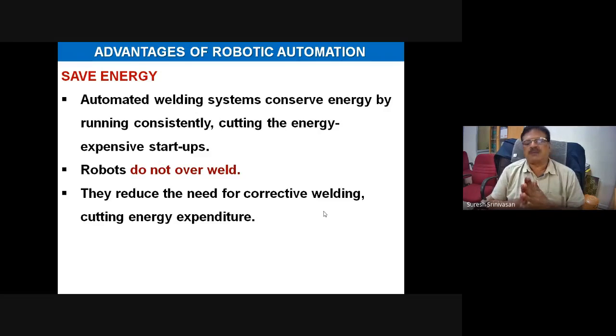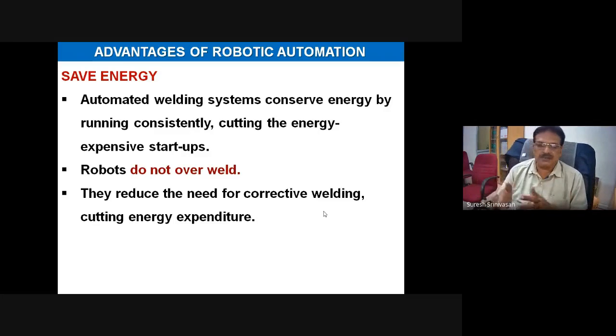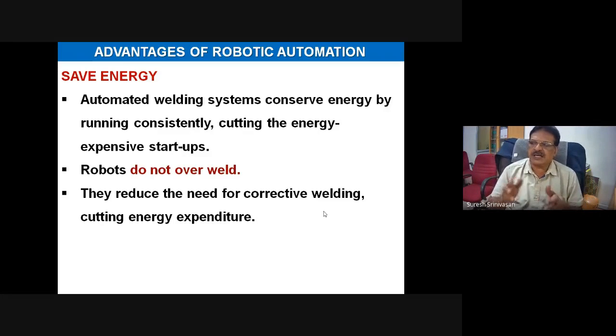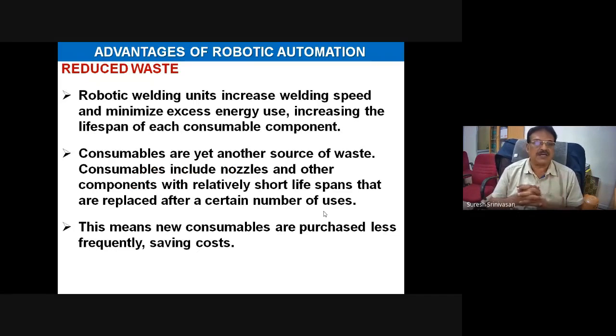No rework percentages. For example, if you take manual welding, you get a rework percentage of 10 to 15%. When you come to mechanization, you can get around 5 to 10%. When you go to robotic automation, this rework can be reduced to below 5%. So there is a drastic reduction in rework from 15% to below 5%. So that is another great saving for your automation, and reduced wastage.